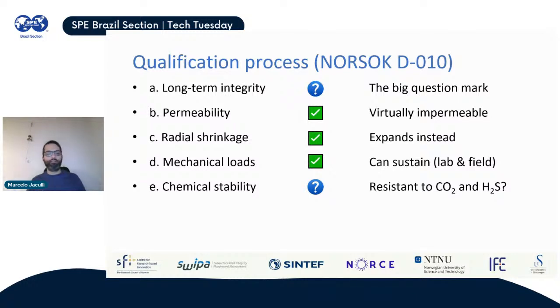Chemical stability is still something up for debate because, for example, if you are talking about pure bismuth, then you don't expect corrosion. It's resistant to corrosion. But after you start adding other elements into the alloy, then it might not be resistant to corrosion anymore. So I think this deserves more investigation, especially for the bismuth-tin alloy, but also for other alloys that the service companies are probably investigating as well. And this is important because you don't want your plug to be consumed by corrosion. So it's something that is still up for debate.